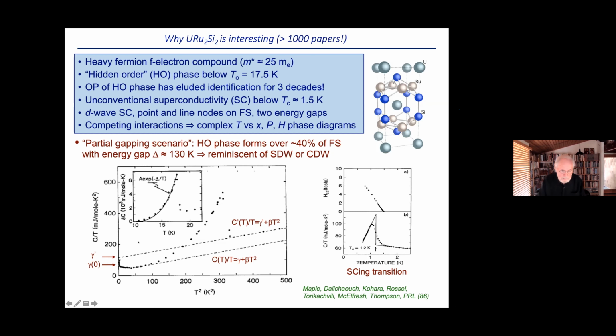And so this represents a reduction of the Fermi surface by about 40%, over which presumably a gap forms due to this hidden order phase. And by looking at this exponential part in the electronic contribution to the specific heat, you can deduce or estimate that the gap is about 130 Kelvin. So here you see onset of superconductivity around 1.5 Kelvin. This is a broad transition. This is a polycrystalline material. And then this is the part of the upper critical field curve right here.